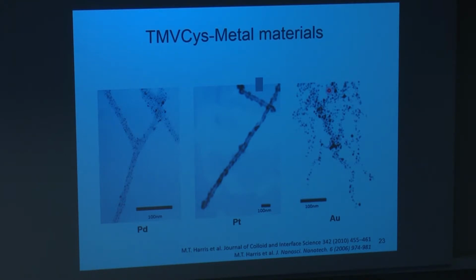But in addition to palladium, there were other metals that we've coated. This is the palladium-coated TMV, and this would be platinum-coated TMV, and this is gold-coated TMV. Now, all of this looks great. And early on, what we were doing, we were using an external reducing agent. And the external reducing agent, if you put that in and you have palladium metal that's not adsorbed onto the surface of the TMV, the reducing agent would reduce the palladium in solution. It would also reduce the palladium that absorbed onto the surface of the biotemplate. And what I noticed is that we would have some material that was coated with palladium, some material that was not coated with palladium. And that was a very inefficient use of the palladium.